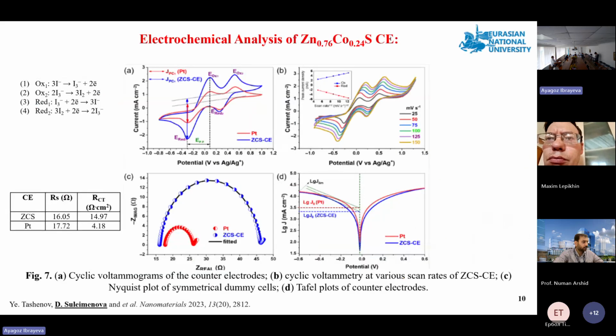The electrochemical performance of the counter electrodes was analyzed using cyclic voltammetry, EIS, and Tafel analysis. Cyclic voltammetry results show that both platinum and zinc cobalt sulfide electrodes exhibit clear redox peaks of the iodide-triiodide couple. Zinc cobalt sulfide exhibits a higher peak cathodic current density, indicating faster triiodide reduction and better catalytic activity. While both electrodes have the same peak-to-peak separation, 0.38 volts, suggesting comparable redox activity. Tests at different scan rates show stable performance and good diffusion of ions.